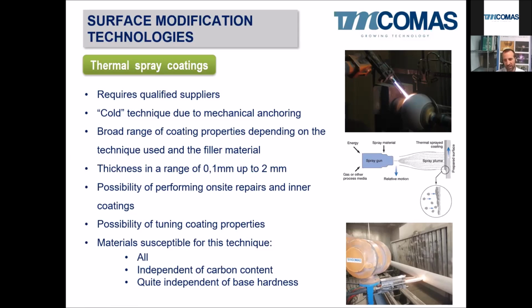At the end, the definition of thermal spray is like painting. It's like painting with a gun. It's like painting with a stream of semi-molten particles. So at the end, you have a gun in which some energy will come, some gas energy, like this flame, or an electric arc, or a plasma arc, to melt the spray material, the filler material that comes in. It can come in the shape of powder or wire. And then there is an atomization and a propulsion of these molten particles to the substrate.